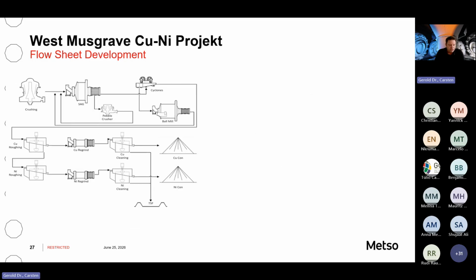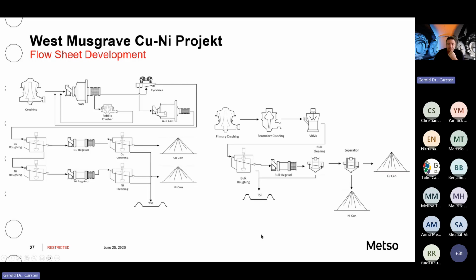So initially, they were targeting a SAG mill ball mill flow sheet with pebble crushing and sequential flotation. But this plant is in the middle of nowhere. It's 600 kilometers away from the next electrical grid, 800 from the next city, so there is really nothing. They were looking for ways to optimize the project efficiency. We carried out a lot of pilot test work together with them, and finally they changed the process in the pre-feasibility stage to primary crushing, secondary crushing, and then VRM for grinding, followed by bulk flotation and regrinding.